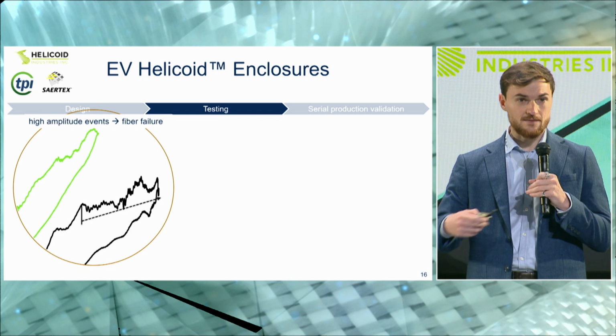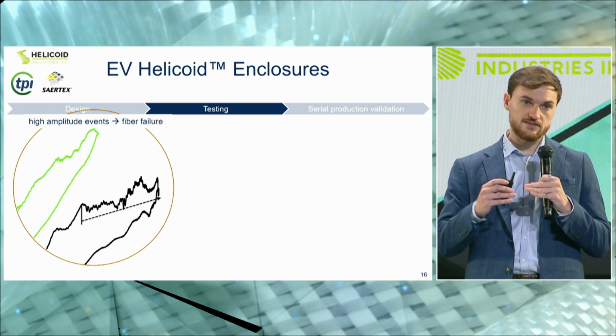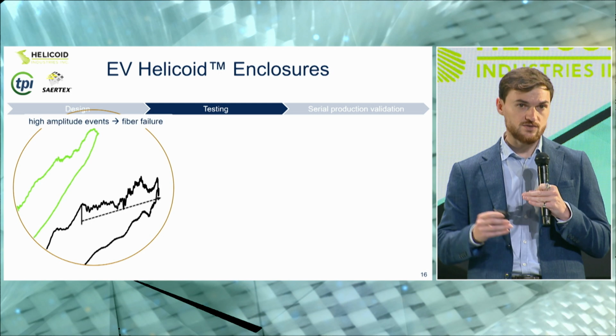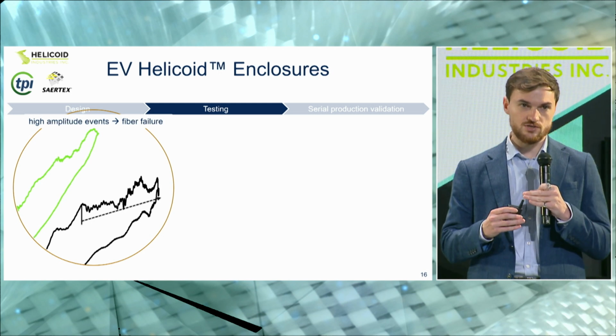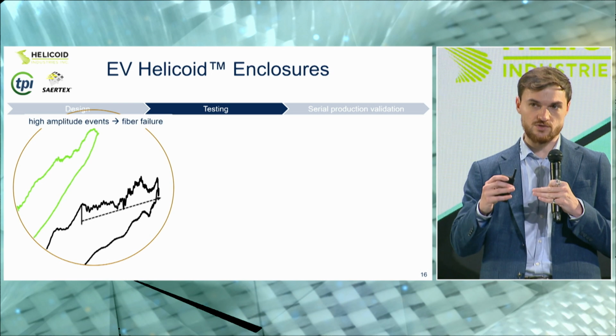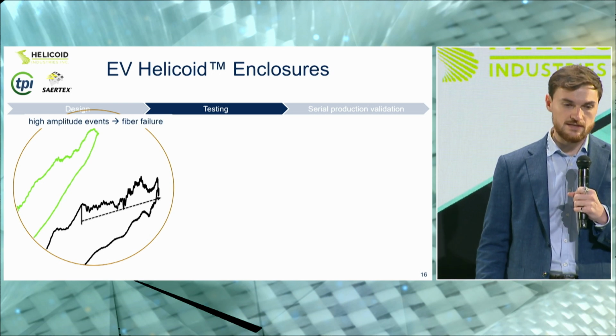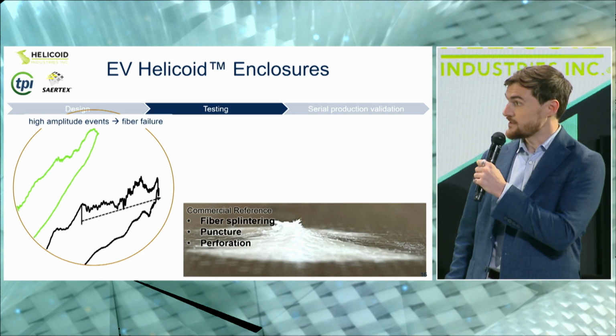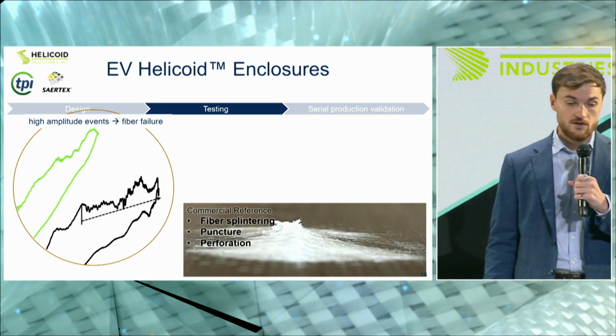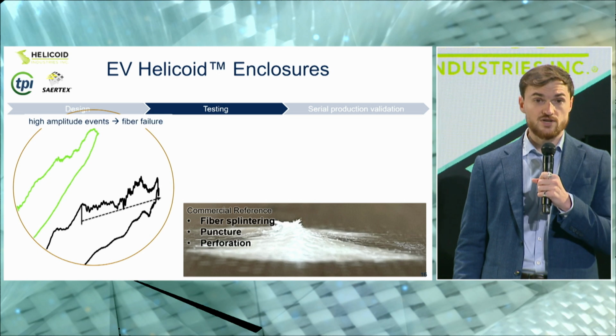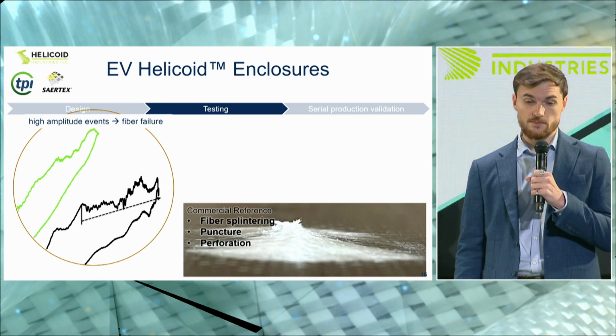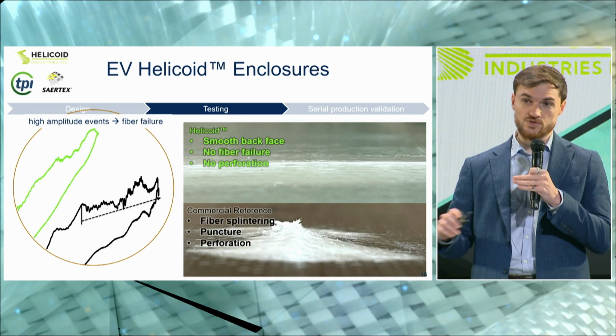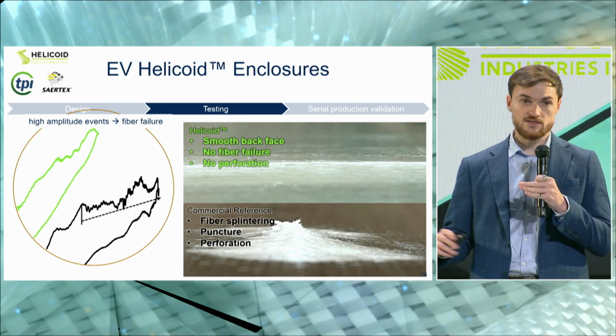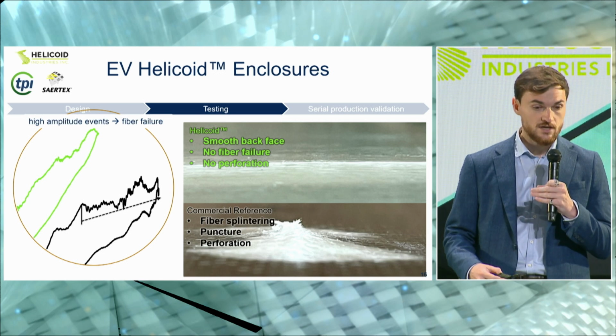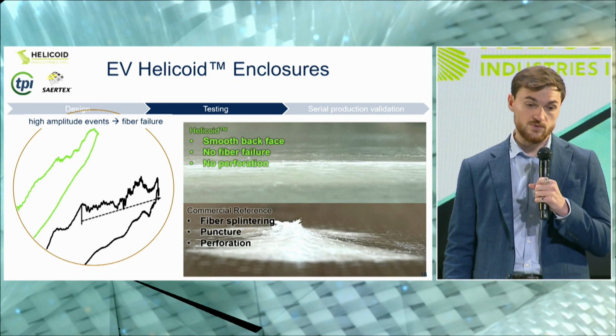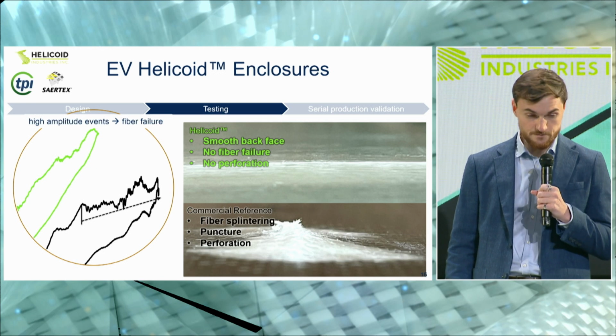And in fact, if you look at the back face of the plate, which is the face forward in the battery pack, so it's the one that you don't want to have any damage on it because it would reduce the clearance that you have with your battery pack, you will see that in the commercial reference, you have a clear puncture with a fiber failure, which suggests very poor structural integrity and poor resistance to a secondary impact, while in the Helicoid you have a very smooth surface, just matrix splits, so just matrix damage, as I showed you earlier, and a much higher structural integrity with no sign of perforation initiation.